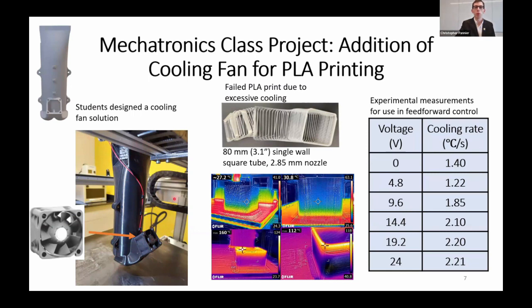PLA printing. When you print PLA, the glass transition temperature is quite low. It's about 60 Celsius. And PLA will crystallize while it's cooling. The crystallization happens most rapidly around 100 to 120 Celsius. So you want to get quickly from your printing temperature in the 180s to 200s down below 60. So you would want to use a cooling fan for the fastest cooling and the least crystallization.